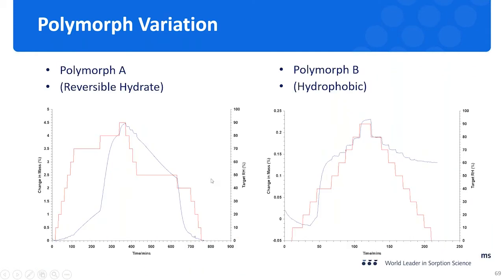And the same, we can also do for different polymorphs of the same sample, which will give a different behavior of moisture sorption. So the polymorph A will show an uptake of about 4.5% with a significant increase at a single step, which indicates a reversible hydrate formation. And in the case of polymorph B, it only takes up about 0.2% for the whole range of humidity, which is a hydrophobic behavior for this polymorph B sample. And with the DVS technique, we can easily detect the difference between different polymorphs.